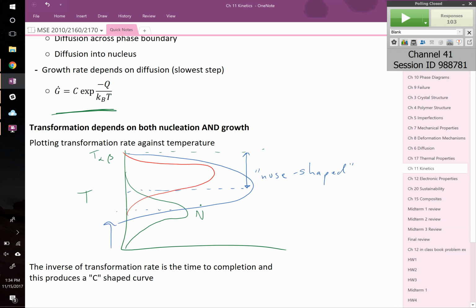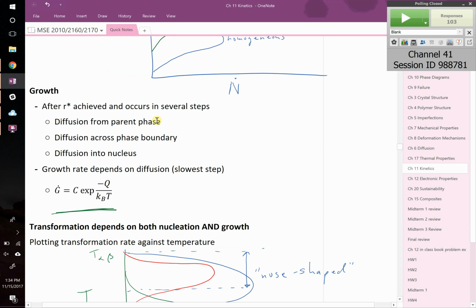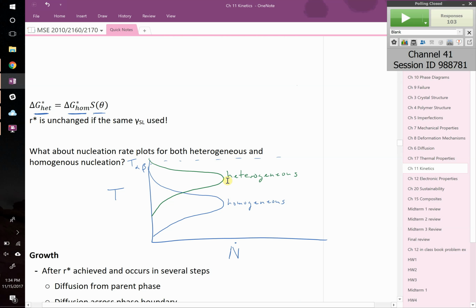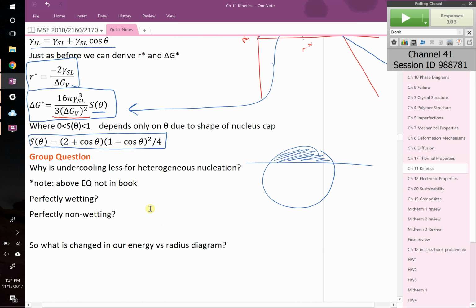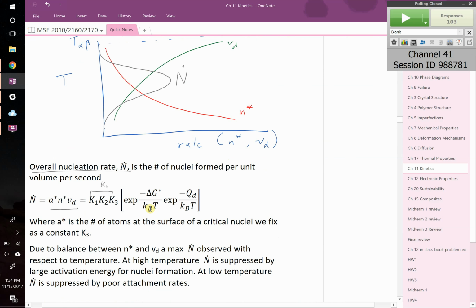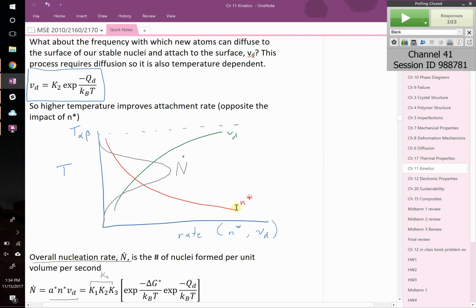Nucleation versus growth. Yeah, Rosa? Why is heterogeneous nucleation, why does it happen slower at the same temperature than homogeneous? It should happen faster. Well, the rate should look like this. At temperatures close to the transition point, it should be way faster than homogeneous, right? But when you go down in temperature, you now have passed the point where diffusion, basically, just like before, you've got this tradeoff between attachment rates and number of nuclei. So you might have lots and lots of nuclei down at low temperatures, but you're going to have a lower attachment rate.